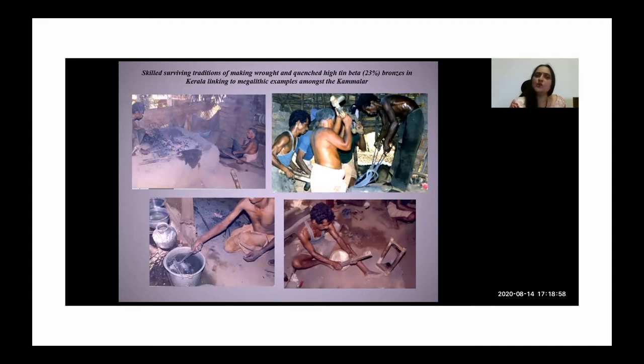But what was additionally interesting was that using ethno-archaeological studies, I was able to actually identify certain surviving traditions of bronze working, where they're still hot working, forging and quenching these vessels made of this beta phase composition of 23% tin bronze. And that was also quite important to have identified this local tradition, because if there's been such a long-standing, continuing tradition, with such close parallels perhaps, then it's quite likely that this was a long-standing, continuing indigenous tradition, and we don't need to necessarily regard the South Indian or Indian examples of high-tin bronzes as exports from elsewhere. So that's where ethno-archaeology comes in handy.